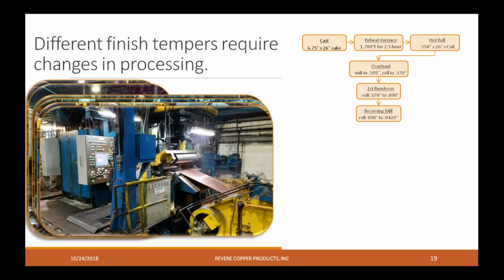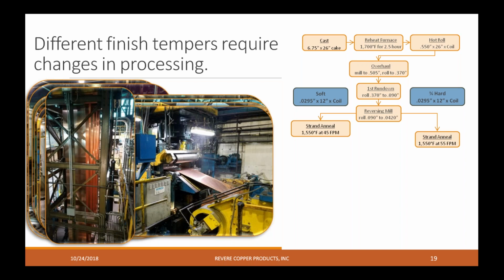We can continue to roll that metal. And in this example, we roll it down to 0.042. So now we haven't had any anneals since that 0.505 gauge. And it's very, very hard metal. So for this example, we're trying to make 0.0295 gauge, and I'm going to show you soft on the left side and 3/4 hard on the right side. So the next step is to anneal it. It's gotten extremely hard, and basically we need to anneal it to continue with the reduction.